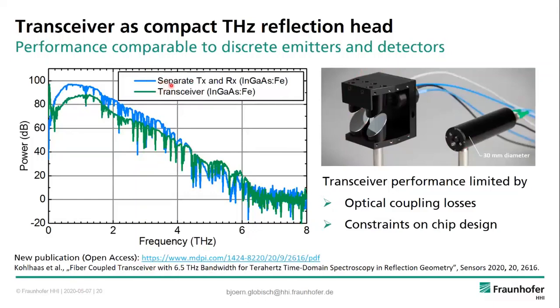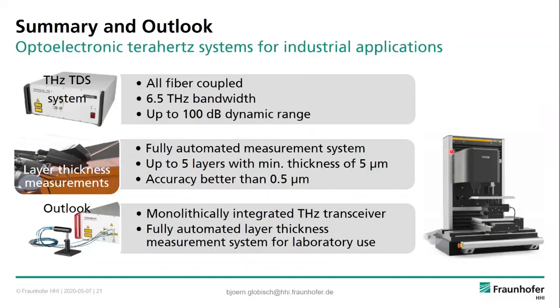So you get with the separated one in blue and the transceiver one in green, more or less the same result. And to our opinion, this is one of the crucial things to get terahertz technology to even more applications in sensing. And with this, I would like to summarize my talk. So I hope I could show you that we have a terahertz TDS system, which is all fiber coupled, covers a large bandwidth, and has a really high dynamic that can be really nicely used for non-contact layer thickness measurements. And I showed you an application of car paint thickness measurements with up to 5 layers. And we get minimal thicknesses of 5 microns with an accuracy better than 500 nanometers.